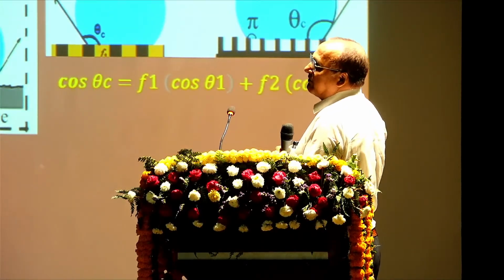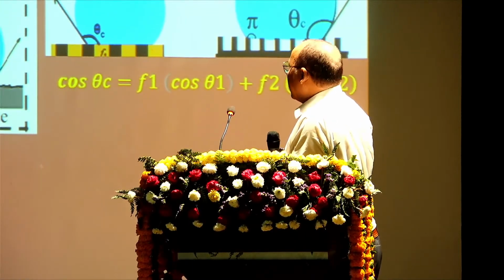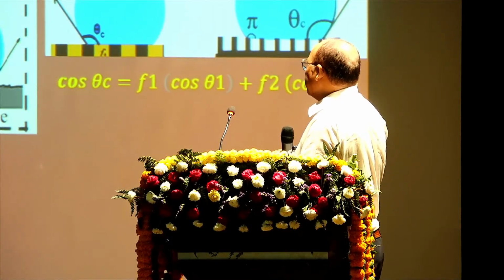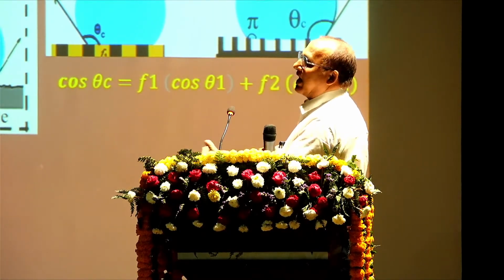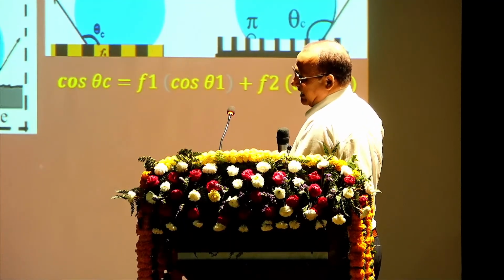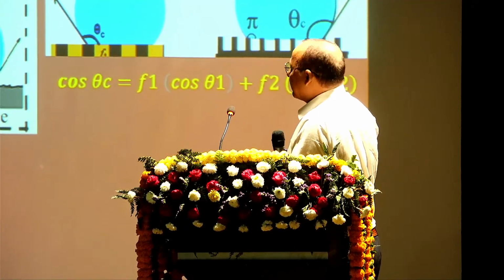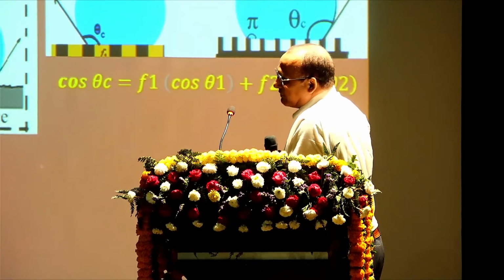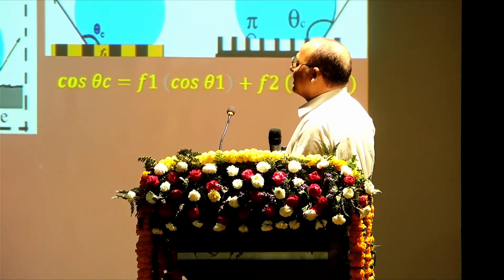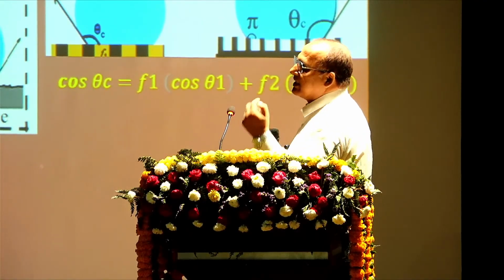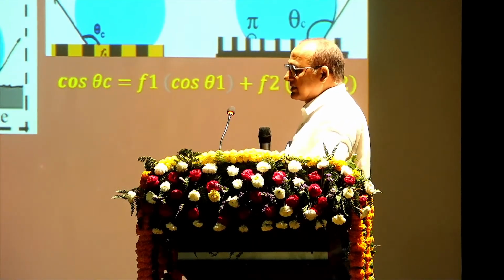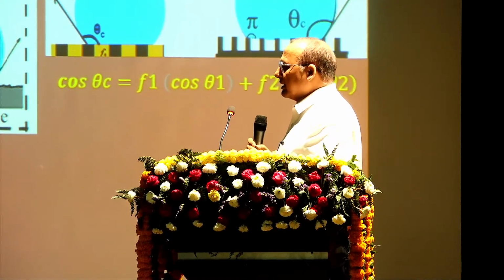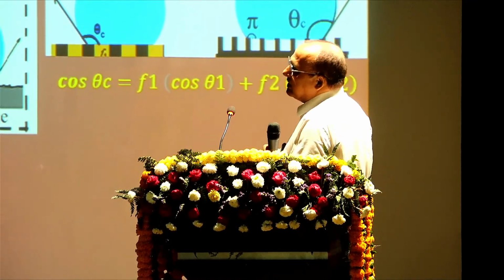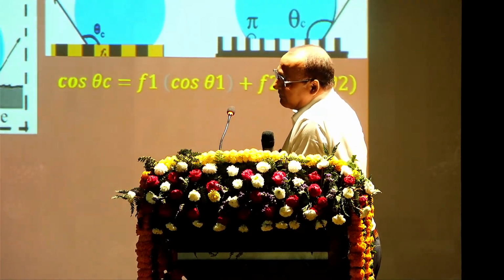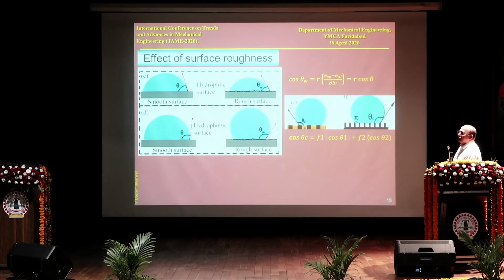If the drop is in a Wenzel state on a rough surface, and you increase the surface roughness, then it becomes more and more hydrophilic. If the drop is in a Cassie state, like on a smooth hydrophobic surface, and you increase the roughness, then it enhances the super hydrophobicity of the surface. Apart from this, if there is a Wenzel state, it means the droplet penetrates the roughness, so it provides a large contact angle hysteresis. So generally on a super hydrophobic or hydrophobic surface in Wenzel state, dropwise condensation is not preferable. Next slide.